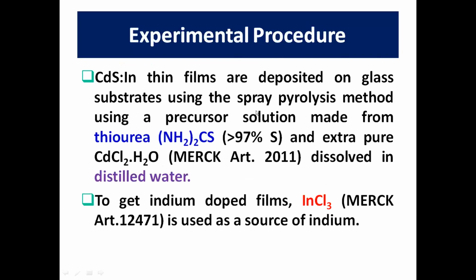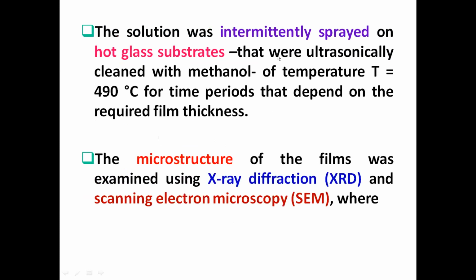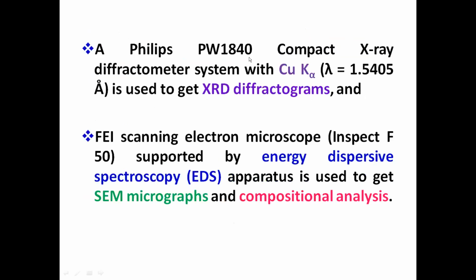Cadmium sulfide thin films were prepared by spray pyrolysis using thiourea and cadmium chloride dissolved in distilled water. Indium chloride is used as the source of indium. The solution was sprayed intermittently on hot glass substrates, and the microstructure of the films was examined using X-ray diffraction and scanning electron microscopy. A Philips PW1840 compact X-ray diffractometer is used, where the Cu K-alpha line is used to get the diffractograms. An FEI scanning electron microscope that supports an energy dispersive spectroscopy apparatus is used to get SEM images and compositional analysis.